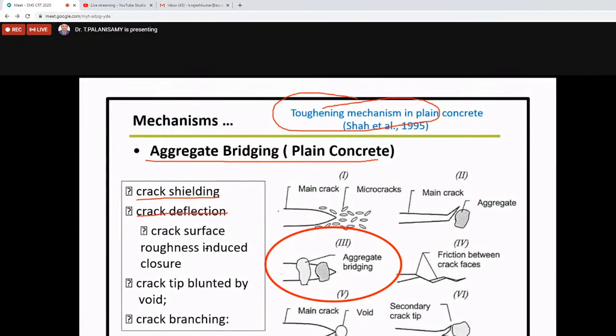Now I can represent this here. Look at this figure. This is the main crack. There is always some place with a macro crack also, and there is a micro crack. So you can see this kind of discontinuity between the cracks inside the concrete. We can see this kind of crack even in the CSH also. That is a microstructural characteristic of the concrete. That is an entirely different study.